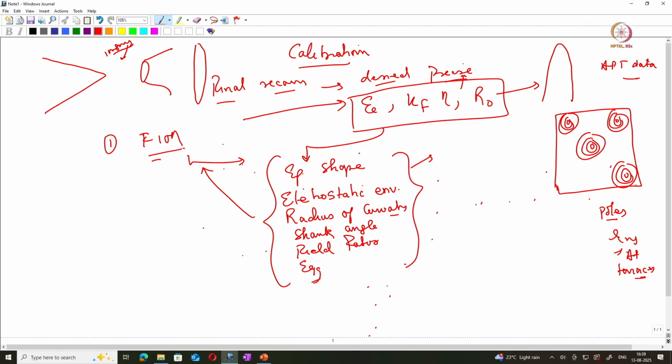If you identify these crystallographic poles, pole 1, pole 2, crystallographically they have a certain angle between the two planes, the crystallographic angle, which is a constant and can be calculated by cos theta.